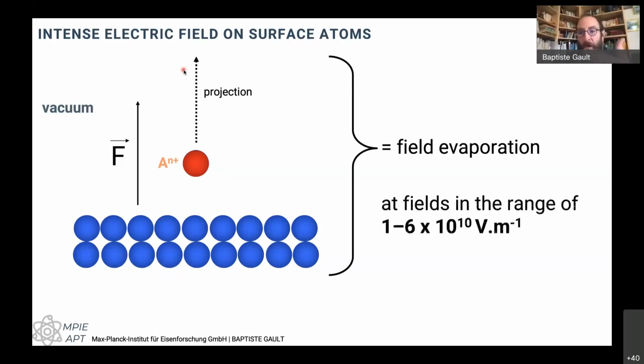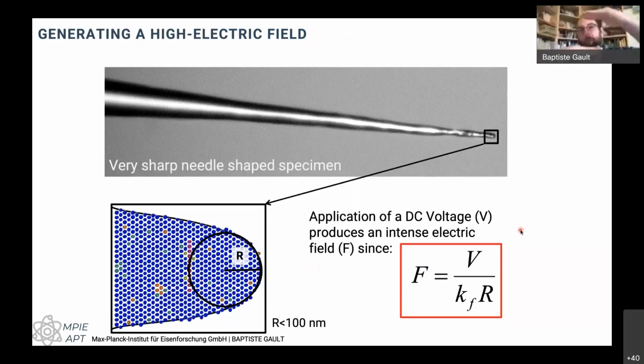And this field evaporation requires fields of typically 10 to the 10 volts per meter, so 10 volts per nanometer roughly, which is not exactly small. It's actually quite big. And how can we generate such fields? We could put 2 plates with 1,000 volts separated by like 100 nanometers, and you probably don't want to be close to this because there might be a lot of other problems associated with doing this. What we can simply do, if you remember some basic electrostatics from undergrad, is take a sphere, put it in vacuum and apply a voltage V; the field at the surface of the sphere would be V divided by the radius of the sphere.